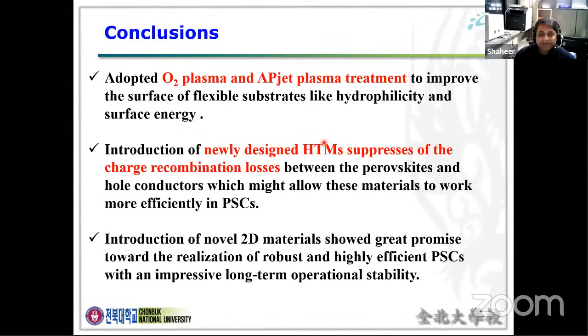So now the conclusion of my talk: by adopting new technology like oxygen plasma and APjet plasma treatment, we can improve the surface of flexible substrates as well as glass substrates, improving hydrophilicity. We can also design different types of small organic HTM materials, which can suppress charge recombination. And in recent years, novel 2D layered materials show great promise towards the realization of robust and highly efficient perovskite solar cells with impressive long-term operational stability. So thank you very much.